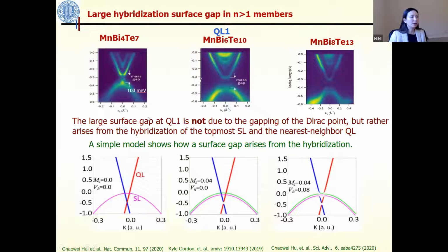But then we realized this large gap. Initially, we thought it was a gapped Dirac cone, but after a closer look into the DFT calculation, it turns out this large surface gap is not a gap of the Dirac cone, but rather a so-called hybridization gap induced by the hybridization effect between the SL layer and the nearest neighboring QL layer.